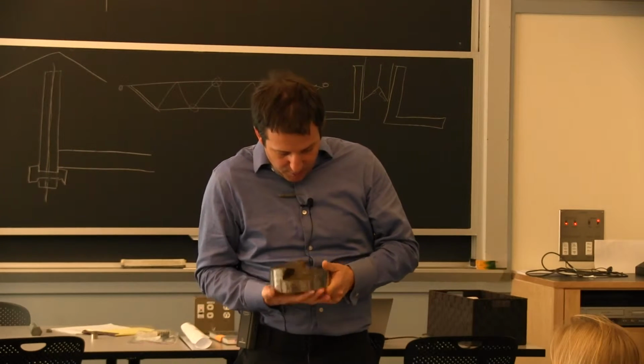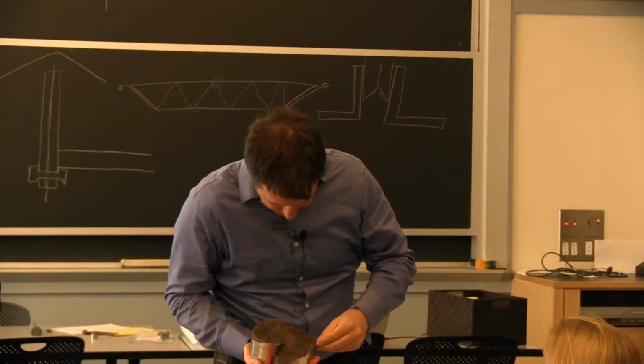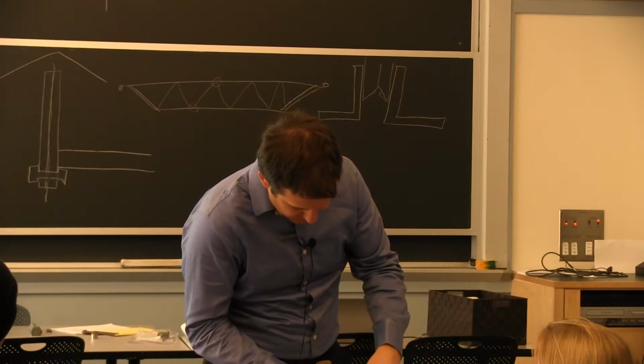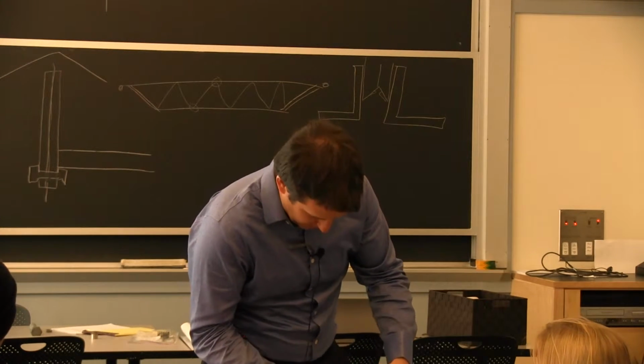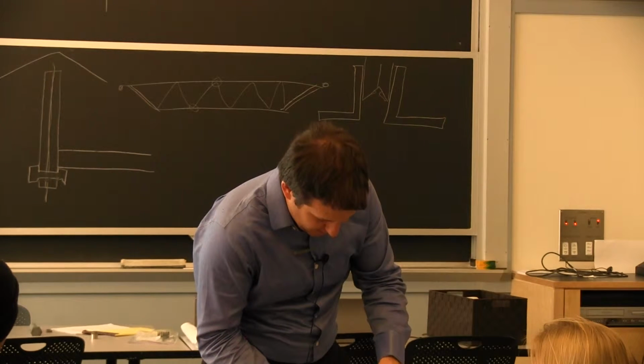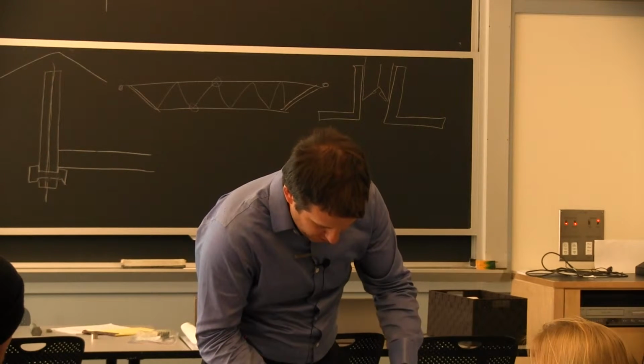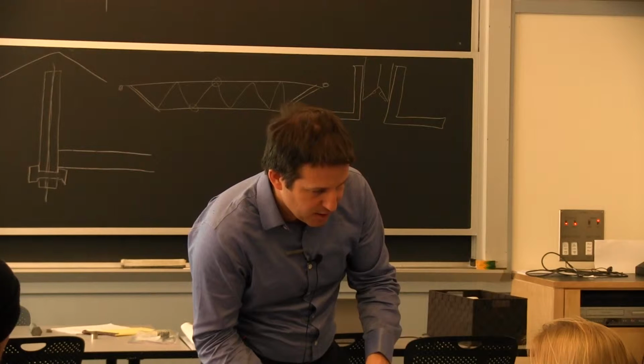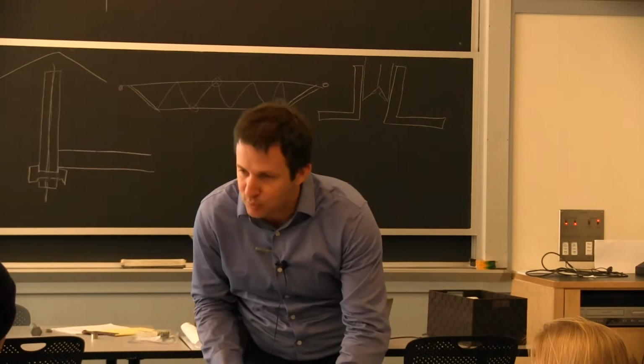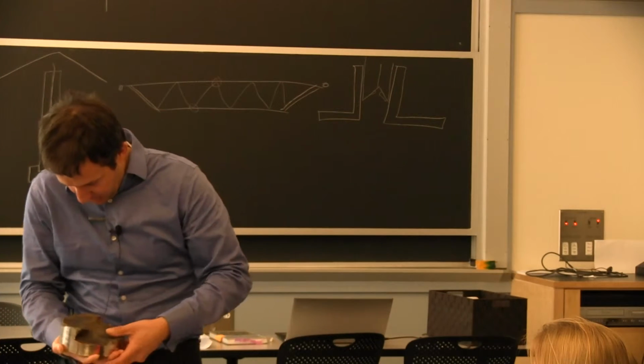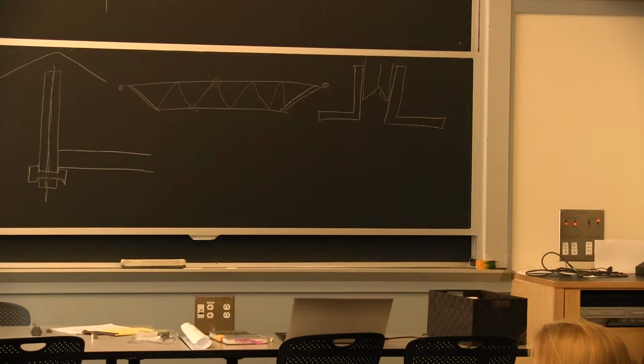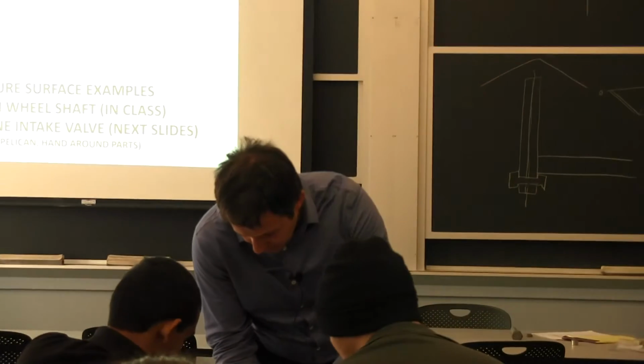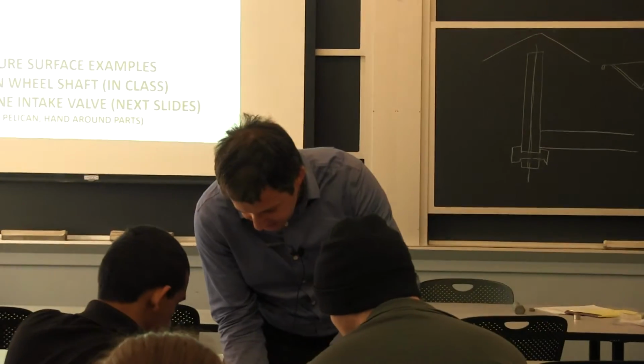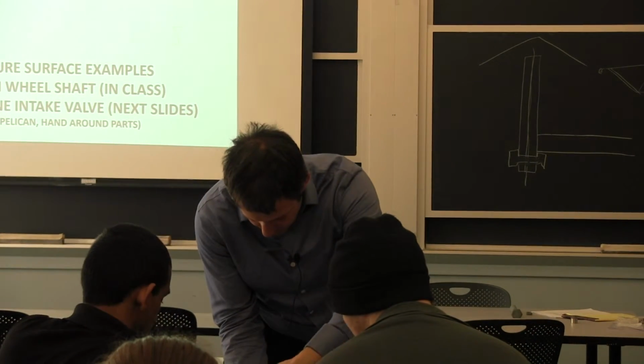There are only two terms in looking at those fracture surfaces. One is crack propagation lines, and you see them: if the initiation is right here, you see a step right here, and it's sort of radiating. There's another step here. These point towards the initiation. Essentially, you start somewhere and it's spreading. So if you look right here, you see these little lines. So you had multiple initiation sites. One crack started here, one crack started there, at slightly different heights, and they were all going that way.